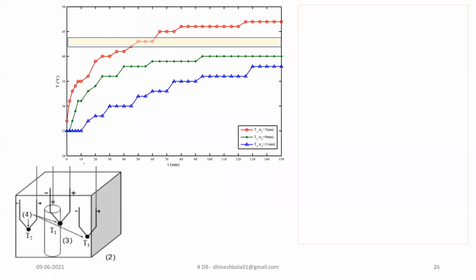And if you just see it, they have placed the thermocouples at three different ranges. One is at a radius of 7 mm, another one is at a radius of 9 mm, and another one is at a radius of 11 mm. So considering this as the chamber and the battery in the center, they have placed the thermocouples at three different radii inside the chamber. So one over here, one in this particular circle, and one in this particular circle. So in all the cases, they have introduced a thermocouple and varied the charging and discharging rate and tried to observe the temperature rise.